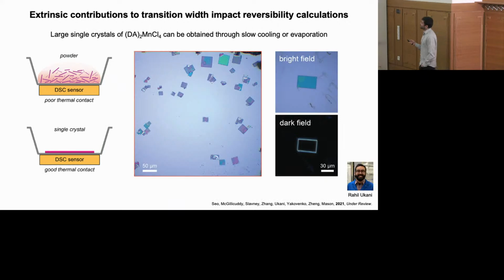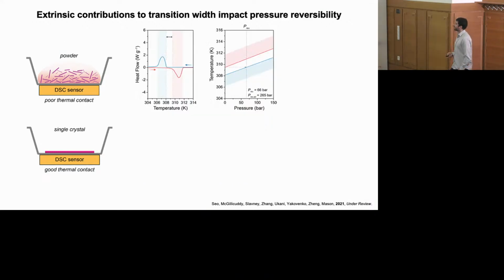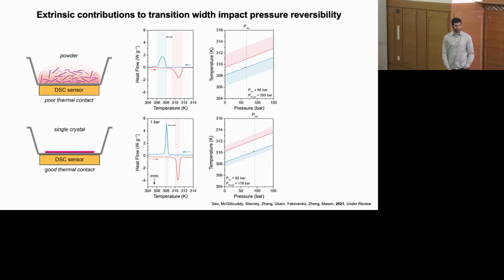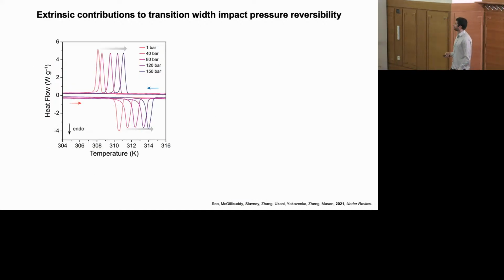If we grow single crystals of these materials, and some of the single crystals that another student in my group, Rahil, has grown are shown here, about 50 to 100 microns in size, and we do these experiments on a single crystal rather than a packed powder, where we have really nice thermal contact between our heat source and heat sink, we see significantly sharper phase transitions. And this is really important for thinking about the amount of pressure that's required to induce a phase transition reversibly, and really emphasizes the importance of thinking about thermal contact when you're thinking about these types of phase transitions in the context of solid-state cooling.